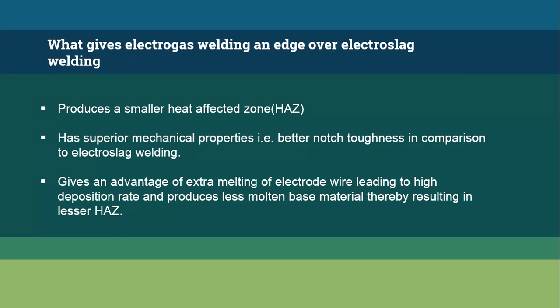What gives electro gas welding an edge over electro slag welding, which are both vertical processes? It produces a smaller heat affected zone, has superior mechanical properties, that is better notch toughness in comparison to electro slag welding, gives an advantage of extra melting of electrode wire leading to high deposition rate, and produces less molten base material, thereby resulting in lesser HAZ.